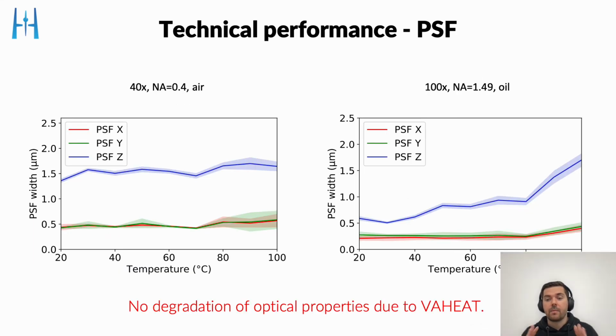But it's also meant for high resolution studies. So we characterized and paid a lot of attention to the optical performance this system can achieve. This is summarized here, which shows, using a 100x 1.49 oil immersion objective, that the point spread function as a function of temperature is not affected by the VAHEAT system.